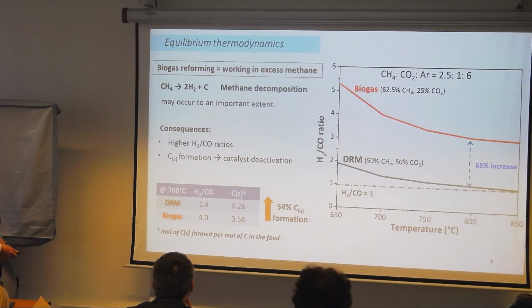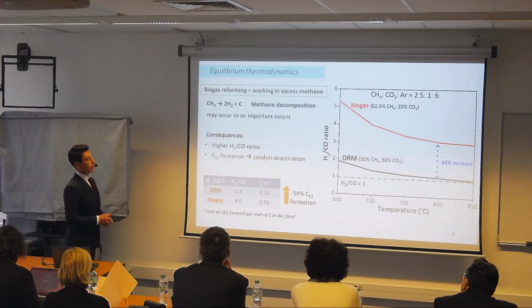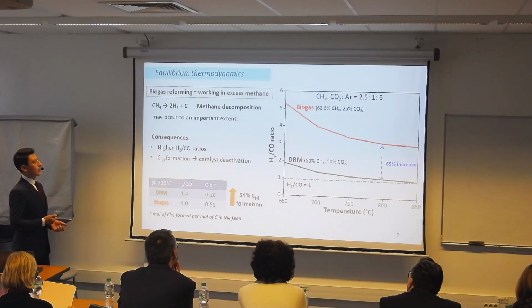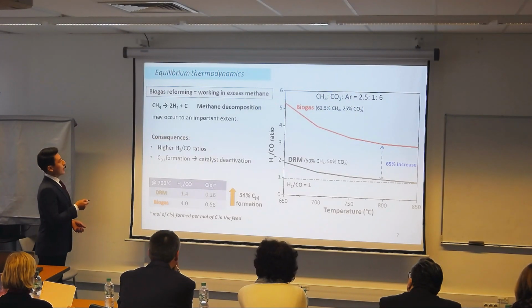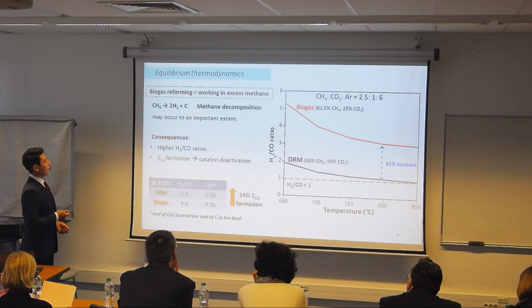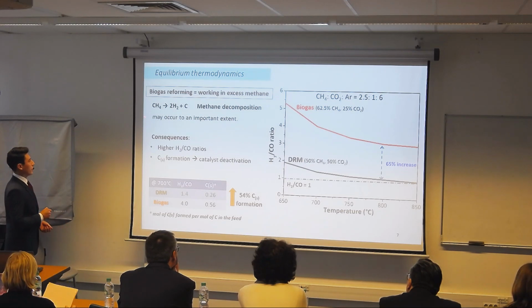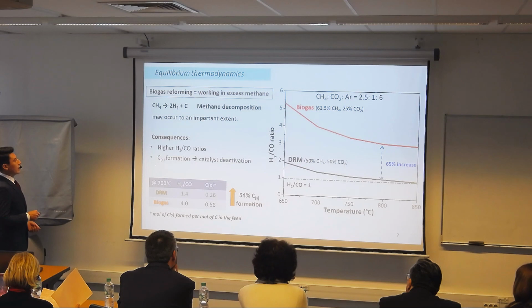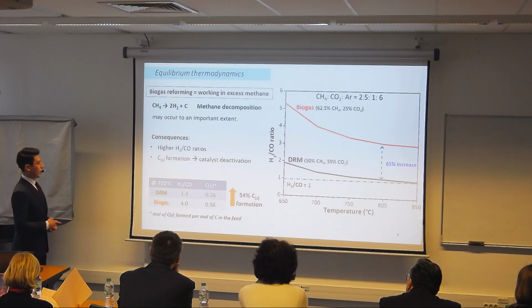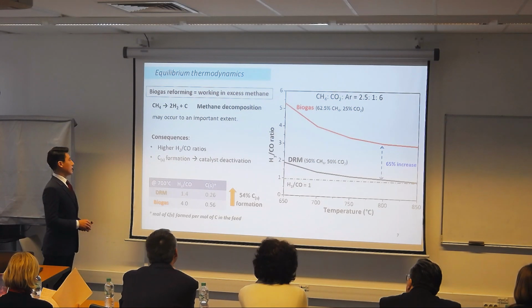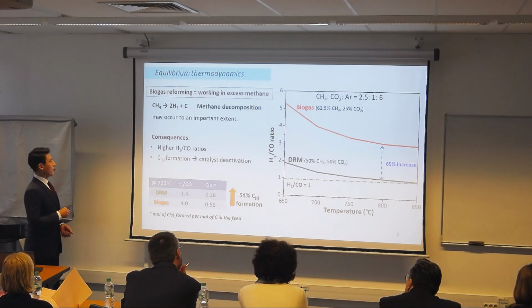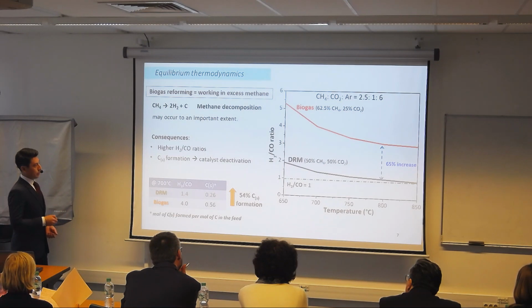So I did some thermodynamic equilibrium calculations just in order to see if these reactions are possible. In the picture here, you can see that the main reaction happening when we have excess of methane, which is typical of biogas, is methane decomposition in the first place. That translates, as you can see, into a high formation of carbon on the catalyst, which may lead to catalyst deactivation. However, we have a higher syngas ratio when we are using biogas.